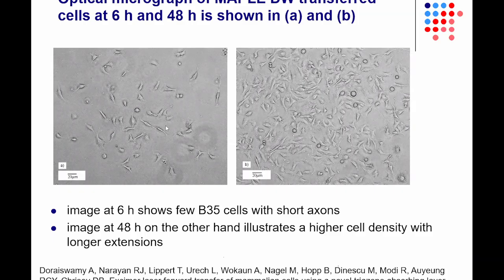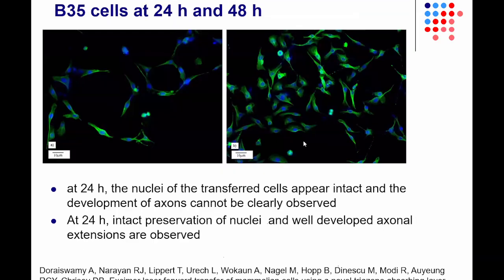You don't see very many connections between the cells, but then you can see a higher amount of cell density with longer axonal extensions at 48 hours. Here you can see, again, some examples of transferred cells, and at 24 hours, the development of the axons isn't clearly observed, but at 48 hours on the right, you have much more well-developed axonal extensions. This is 24 hours on the left and 48 hours on the right.